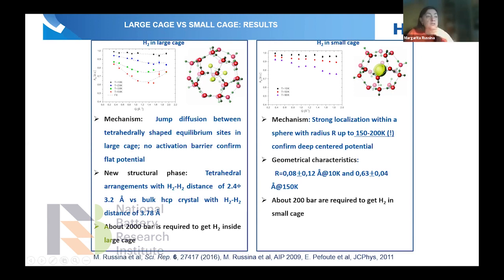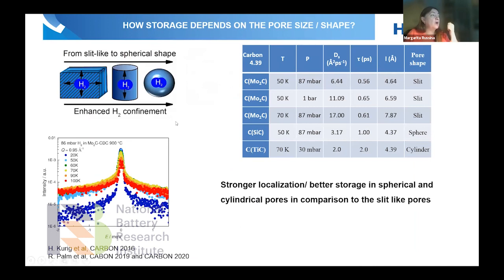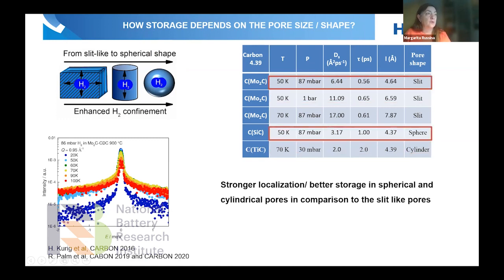Okay, the same effect we also see, we can use this effect for this microporosity and size-shape for the storage effect. For instance, we looked also at the diffusion. I think I have to place it in here because you won't see. Yeah, we looked at the diffusion of hydrogen in this microporous metal-derived carbon, where the pores were defined of different shapes, and we found that the best diffusion you see here.